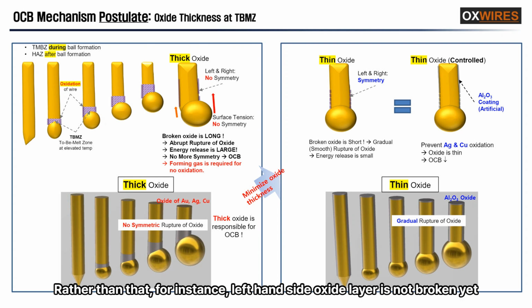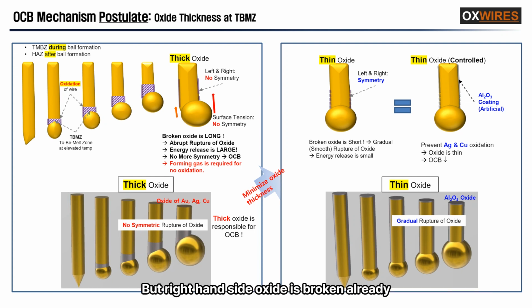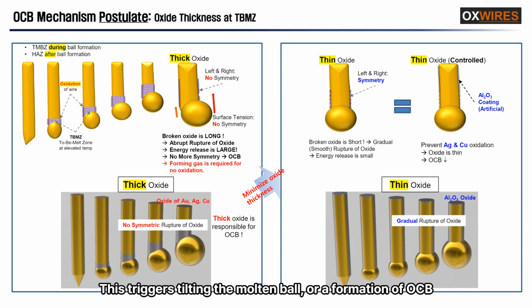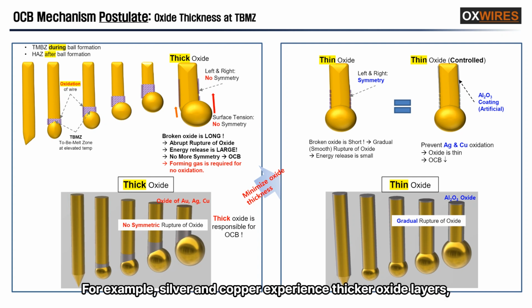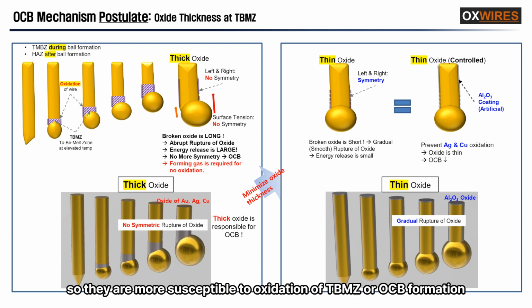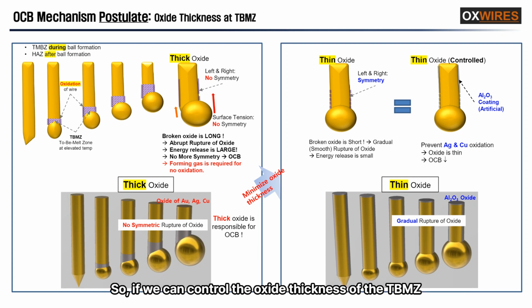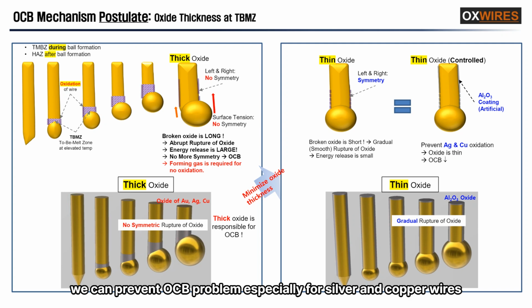Rather than that, for instance, left-hand side oxide layer is not broken yet, but right-hand side oxide is broken already. As a result, there is no more symmetry or axisymmetry. This triggers tilting the molten ball, or a formation of OCB. For example, silver and copper experience thicker oxide layers, so they are more susceptible to oxidation of TBMZ or OCB formation. So, if we can control the oxide thickness of the TBMZ by making use of our aluminium oxide coating, we can prevent OCB problem, especially for silver and copper wires.